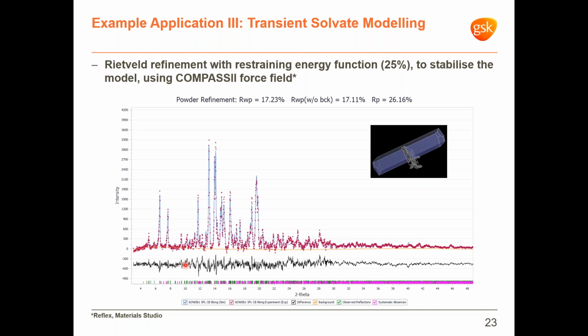Also, limitations on the solvent modeling must be highlighted, as the solvent is very likely to be disordered, thus making the geometry optimization quite problematic. Nonetheless, the refinement can be considered satisfactory in confirming the nature of the intermediate transient solvate, and most importantly, shedding some light on this form transition.